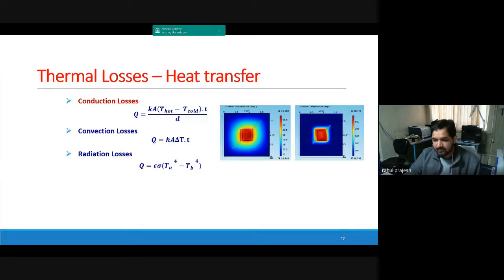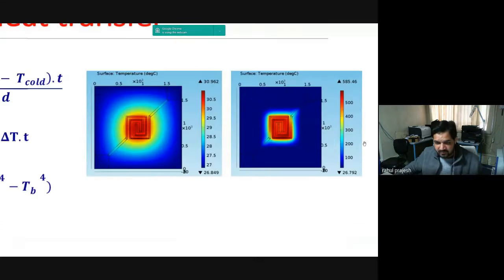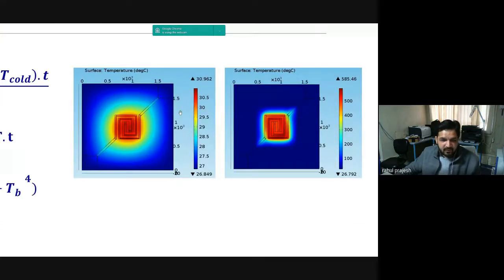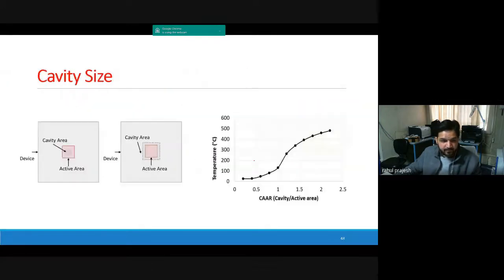Now, just to give you an example, I will show you these two simulations. The first simulation is this one, which has no cavity at the back side, and it gives you only 31 degrees centigrade. So initial was 26, 27, and now 31 degrees. But for the same power consumption, in the second case, when you make the cavity at the back side, the temperature is now around 600 degrees centigrade. So that's the advantage of reducing the conduction losses. We just tackled the conduction losses, and now we see a very good increase in temperature.